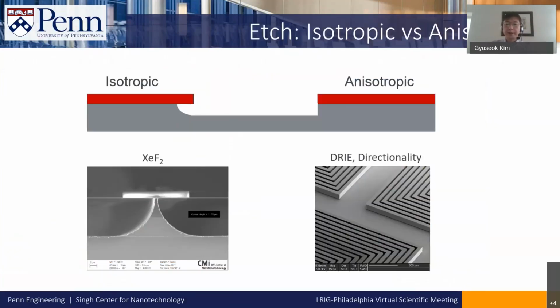The next step is etch. There is one important concept: isotropic etch versus anisotropic etch. In the case of isotropic etch, the etch rate of the material is independent of direction. For example, as you can see on the left side, if you etch silicon with xenon difluoride, you get such an undercut. But if you use a reactive ion etch tool, this is an example of the RIE tool, we will discuss this later, we can etch with some directionality. So we can make a very vertical sidewall by an anisotropic etching process.